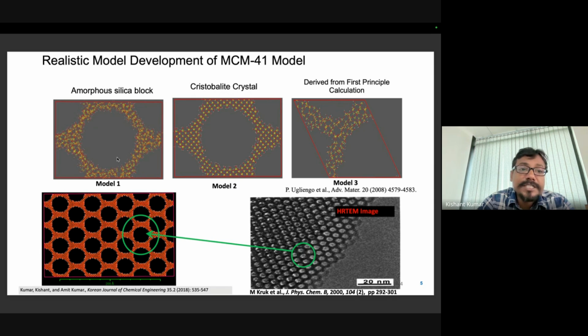And when you replicate this model 1, you will get this picture, which is really a replica of this TEM image. We started this model from a very basic unit cell structure. That unit cell we obtained from the experimental data, and we tried to model that experimental data in the computer, and then we ended up with this model.